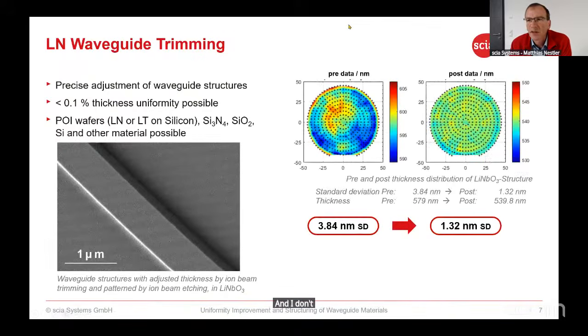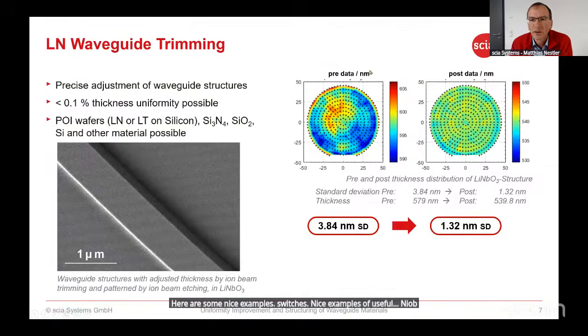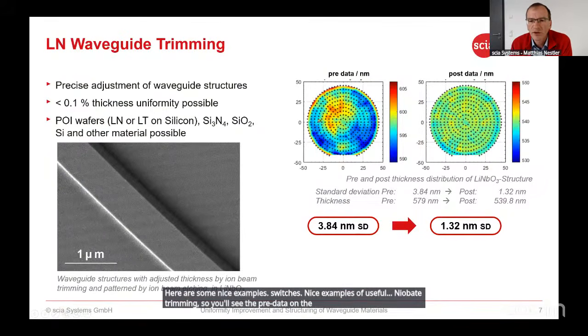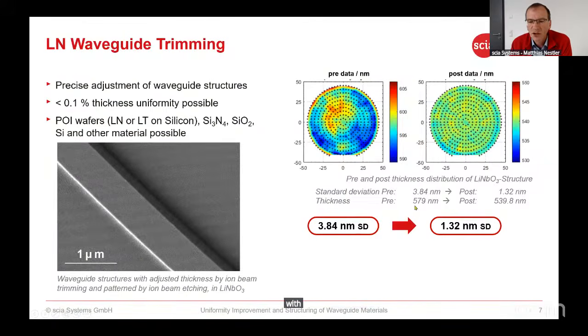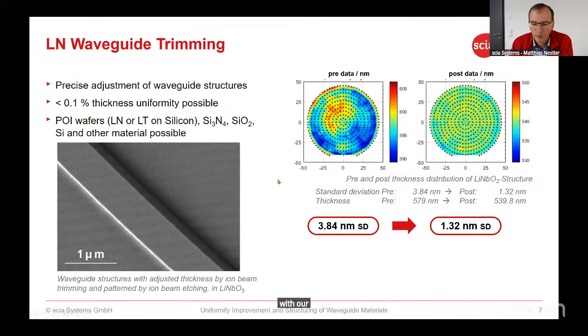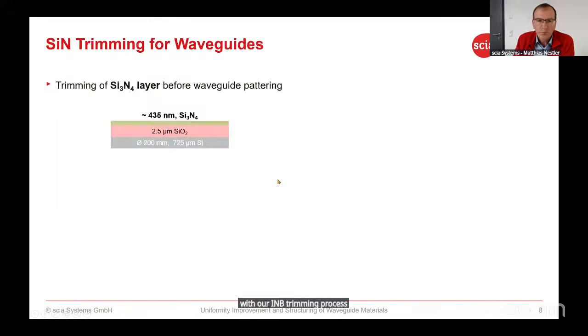Here are some nice examples, just need to switch it. Nice examples of lithium niobate trimming. So you see the pre-data in the left picture with some variation in the thickness, with a standard deviation of 3.84 nanometer, and this could be trimmed down to 1.32 nanometer standard deviation with our ion beam trimming process. Also, silicon nitride is a material that can be trimmed.